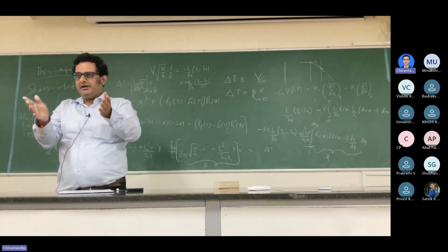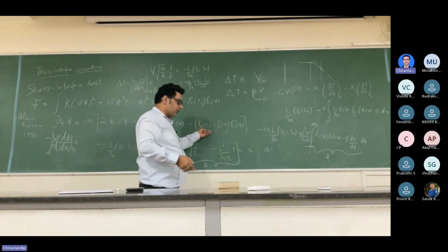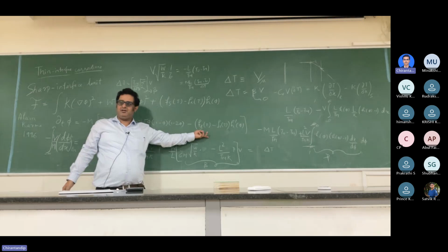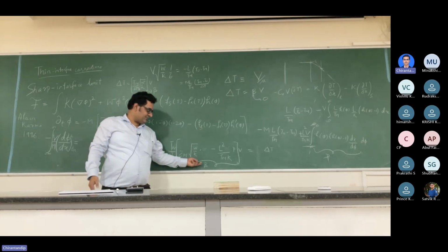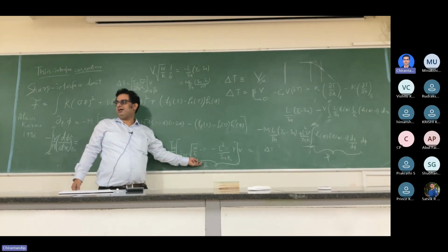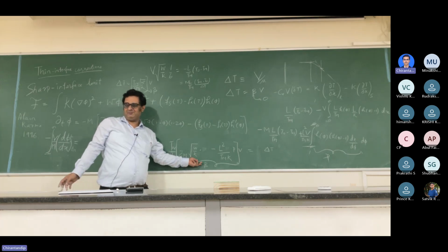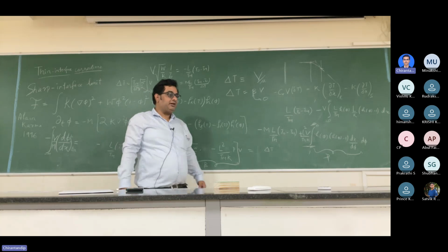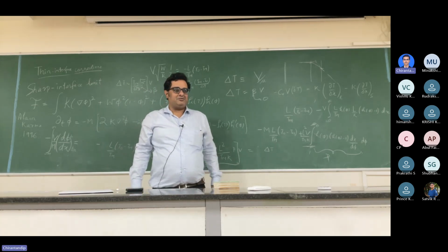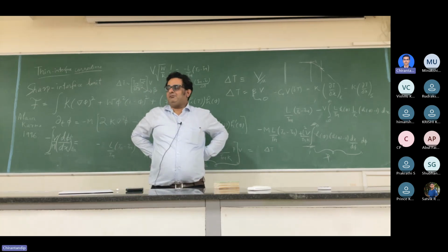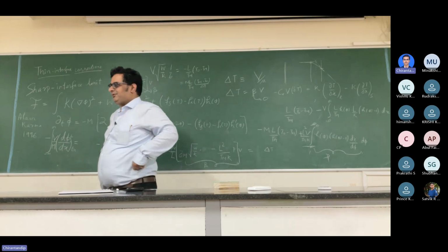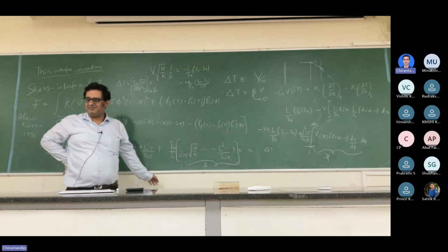But if you're finitely wide, you naturally have to invoke a correction of the driving force at the interface, which will allow the correction of the temperature at the interface to be flexible. Right? That's the idea. Very nice idea. It's an insight which is at some level very difficult to imagine, but if you do it formally mathematically, it's something that comes out.